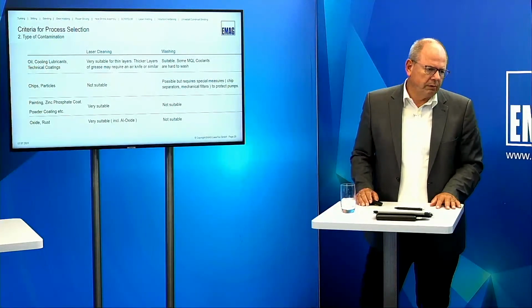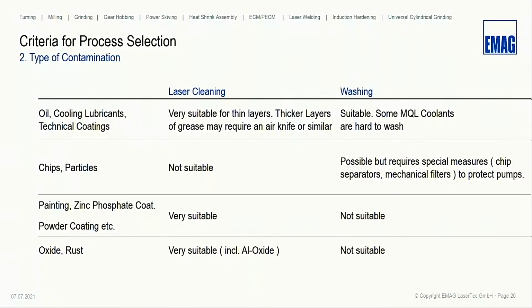Okay, the type of contamination is an important thing. Laser cleaning, this was the previous question, thin coatings. This is a perfect application for laser cleaning. We suggest for thinner layers, it's super. Thicker layers may cause some issues. In washing, oil, cooling lubricants, stuff like this can be washed away. But what we experienced in the past is that some MQL coolants raise problems. This is caused by their chemistry.